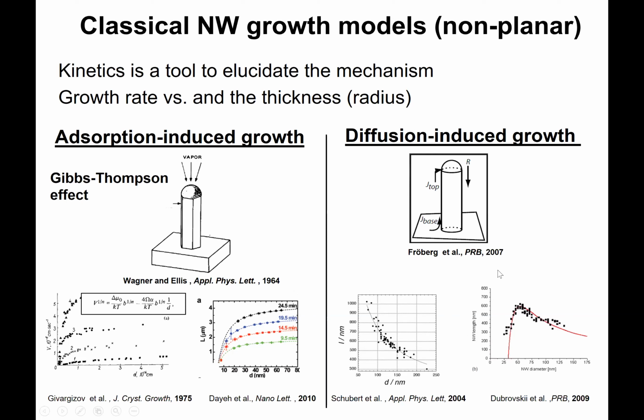But then for larger diameters, it was dominated by diffusion limitation, where what was observed is that the material cannot arrive directly from the vapor phase into the nanoparticle, but has to first absorb on the surface, and then the atoms need to crawl by surface diffusion. They need to slowly crawl along the surface to the base of the nanowire, and then climb the walls of the nanowire until they reach the catalyst.